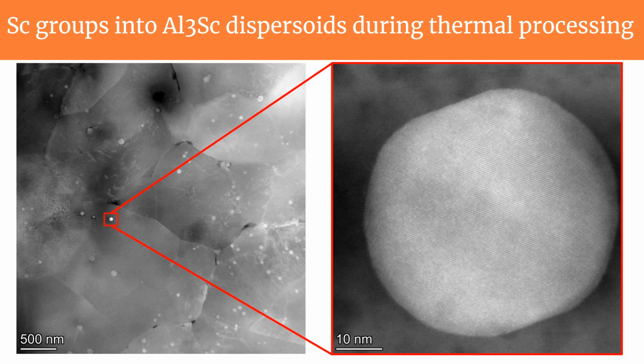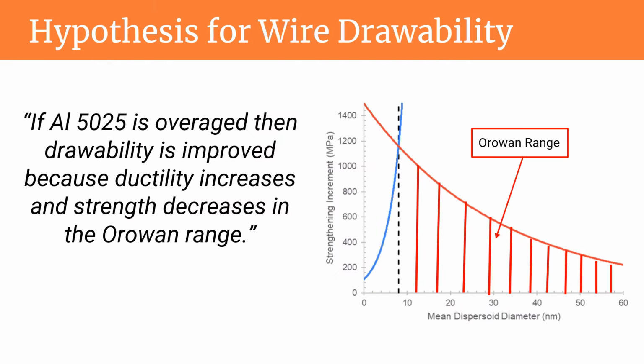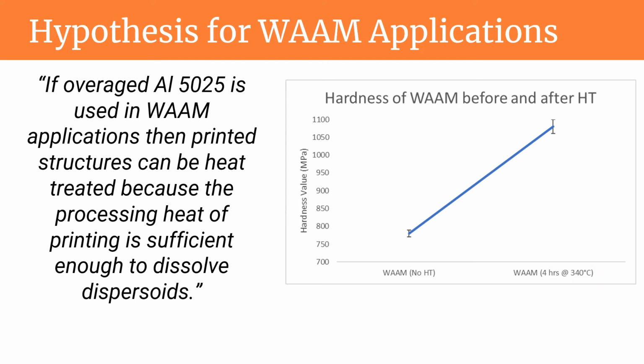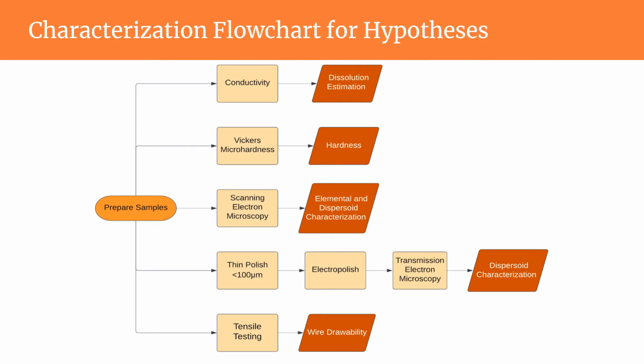In the past, Hobart has had issues with material fracture during wire drawing, as peak-aged 5025 is not ductile enough to undergo the wire drawing process. The problem addressed in this project involved identifying an overaging thermal process for the 5025 rod that allowed for drawability. A secondary problem was also addressed involving subsequent dissolution of Al3Sc dispersoids during WAAM, so the printed part could be thermally processed for increased strength.